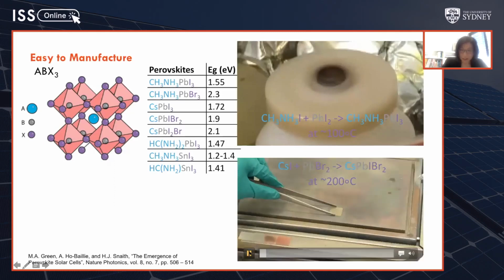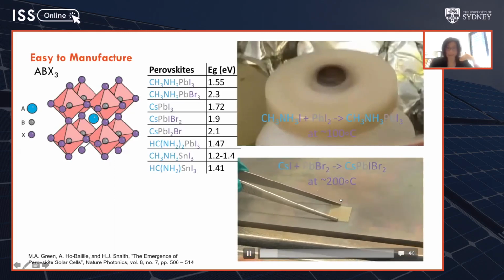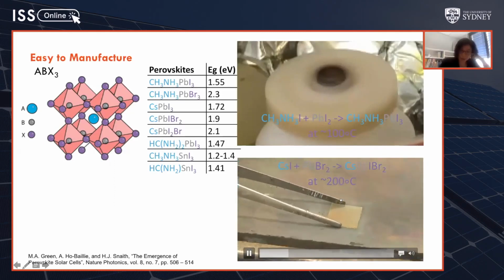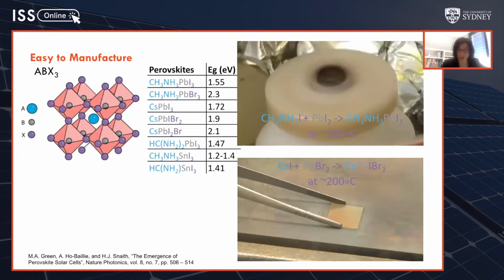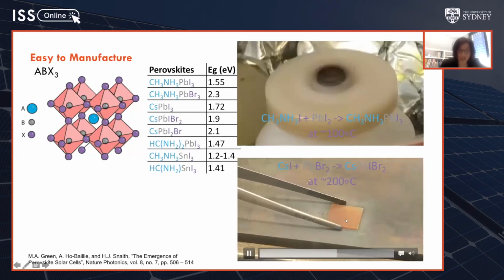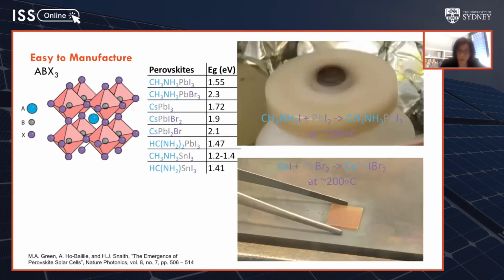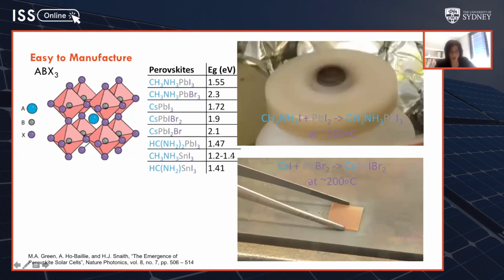The second video shows one of my students making a cesium lead iodide bromide film by spraying the precursor solution onto a substrate, which is sitting on a hot plate at 200 degrees Celsius. And you can also see the instant change to orange, and that's because the film has a band gap of 2 eV, which corresponds to the orange color.